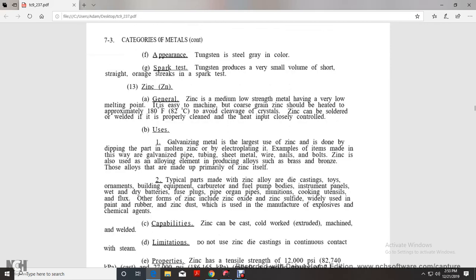Zinc. In general, zinc is a medium to low strength metal and is easily machined. Coarse-grained zinc should be heated to approximately 180 degrees Fahrenheit to avoid cleavage of the crystals. Zinc can be soldered or welded if properly cleaned, with the heat input closely controlled. Uses: galvanized metal is the largest use of zinc, done by dipping the part in molten zinc or by electroplating. Examples of items made this way are galvanized pipe, tubing, sheet metal, wire, nails, and bolts.